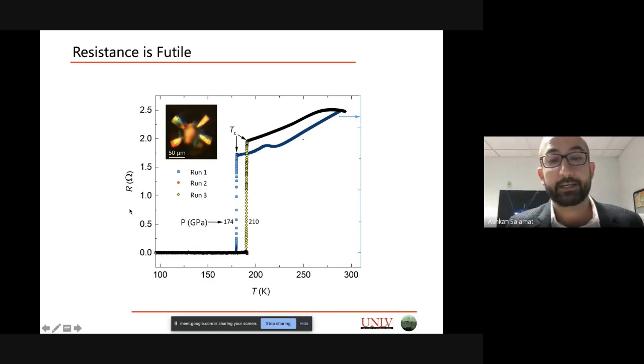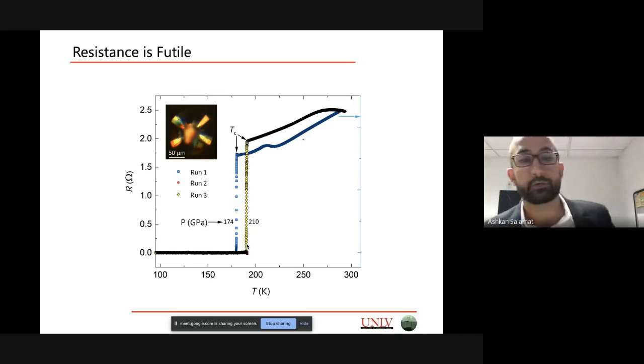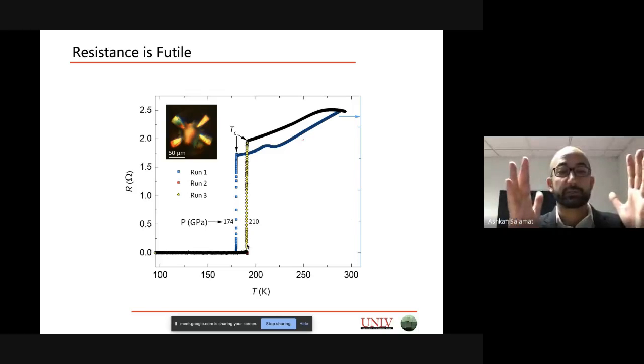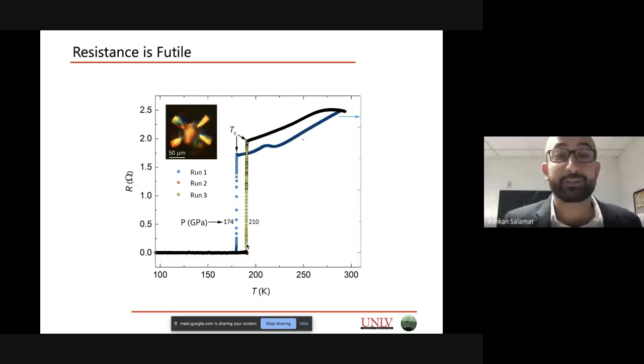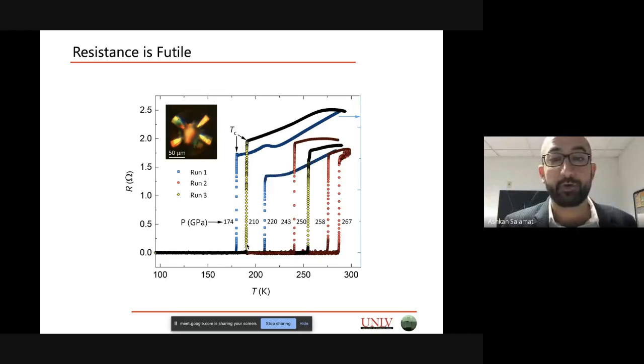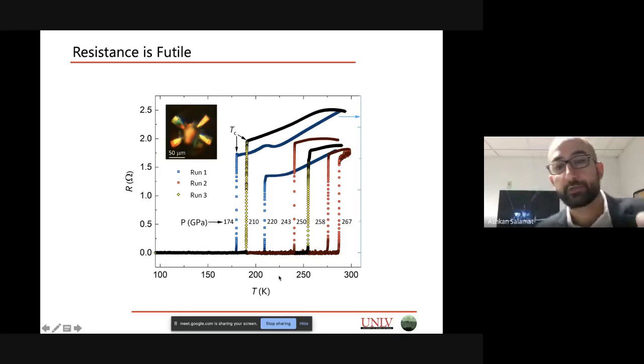What's important here is, as we compress the material, as we squeeze on it harder, and we remeasure this property, the superconducting transition temperature increases. This is a very important observation for us. So you take this material, it's superconducting, and as you squeeze it, its superconducting transition temperature increases. And in fact, what we find is these values represent pressure. As you increase the pressure, the superconducting transition goes to higher and higher temperature. So these plots move further and further to the right in terms of temperature.